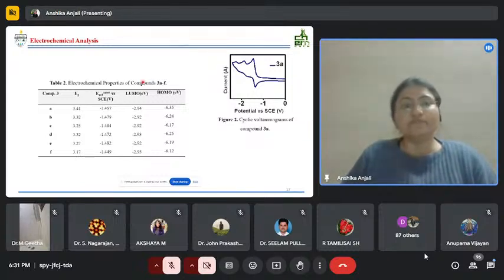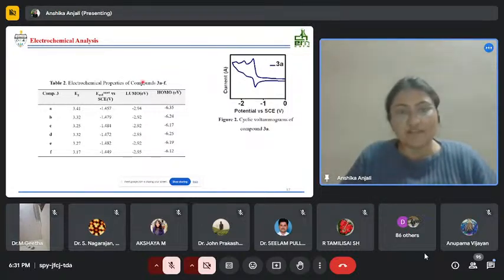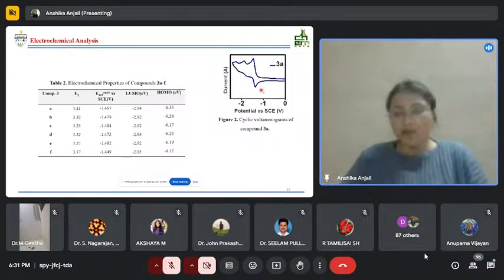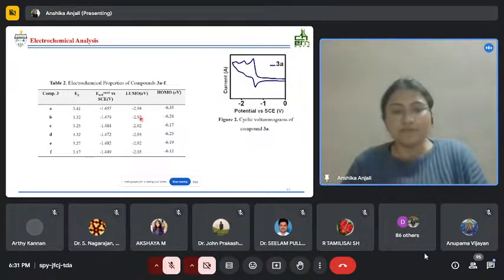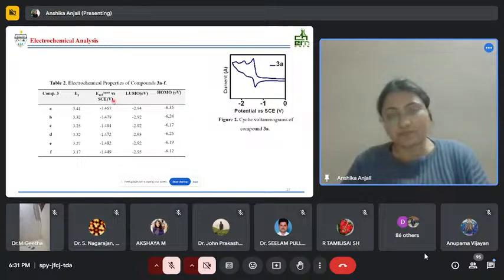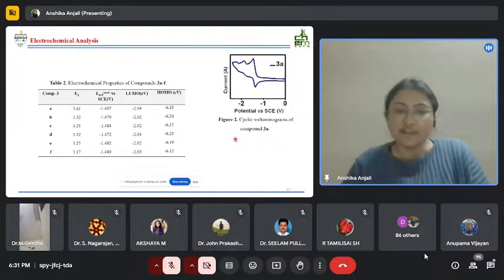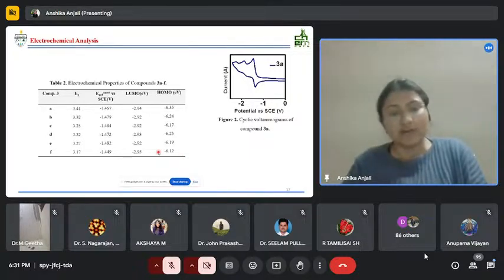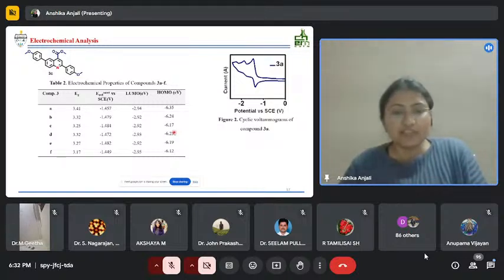So for these compounds, their electrochemical properties like their HOMO-LUMO levels were calculated. To do that, we carried out cyclic voltammetric studies, and we plotted the cyclic voltammograms. For these compounds, we observed peaks only in the negative potential. From their negative potential values, we calculated the LUMO energy levels, and from there we calculated the HOMO and the band gap. For all these compounds, the LUMO energy levels lie in the range of -2.92 to -2.95 eV, and HOMO energy levels were in the range of -6.12 to -6.35 eV. Because of these HOMO and LUMO energy levels, they have the tendency to act as n-type materials. Here, for the dimethoxy substituted compound, we got the highest LUMO and HOMO energy levels.